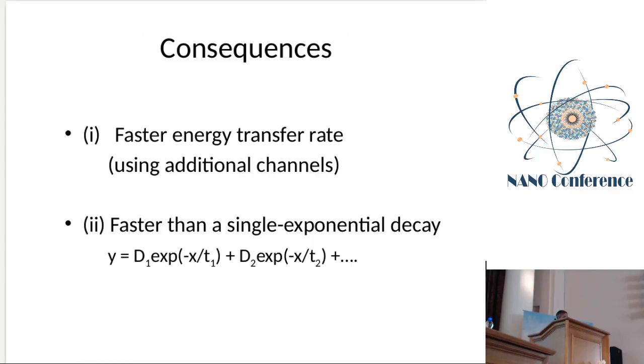For large aggregates, we have two important conclusions. The first one is that there is a faster energy transfer rate using additional channels in large J aggregates, and the second conclusion is that the energy transfer can proceed faster than single exponential decay. Again, because we have different channels through which the energy can be transferred.